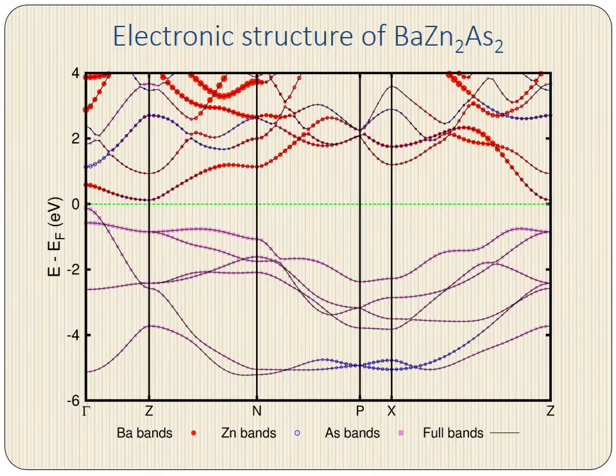This is the band structure, resolved by atomic character for pure barium zinc arsenide. The first thing we note here is that the band gap is small and indirect, equal to about 0.25 electron volts. The top of the valence bands, as you can see here, are primarily of arsenic character, while the bottom of the conduction bands are primarily of barium character. And then mixed in throughout these bands is some of our zinc character.